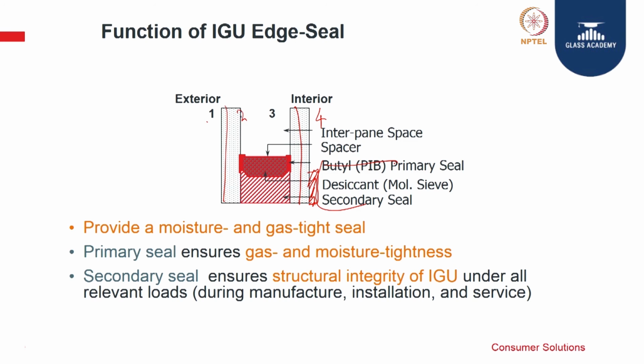Here, if you look, these two are panes, and this is the metallic spacer which has got a desiccant filled in, and the butyl is applied to the edge of the spacer, bonding the spacer to the glass and keeping the spacer in place. The spacer provides rigidity to the DGU in terms of keeping the panes. And the secondary sealant here is the one which provides the structural integrity of the IGU, okay, under all relevant loads, whatever is the load you have.